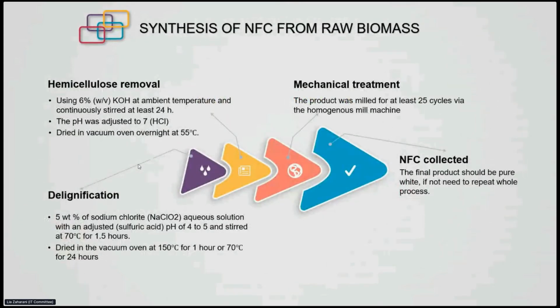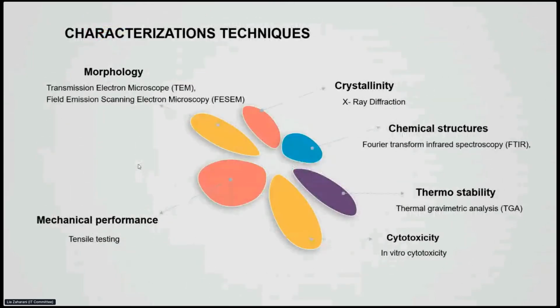For synthesis of nanofibrillated cellulose from raw rubber wood biomass and kenaf-based biomass, above all, hemicellulose removal and delignification, then mechanical treatment. After mechanical treatment, we repeat the drying process, still using a freeze dryer. Then we are able to collect nanofibrillated cellulose. And finally, we use a mechanical performance test, tensile testing.